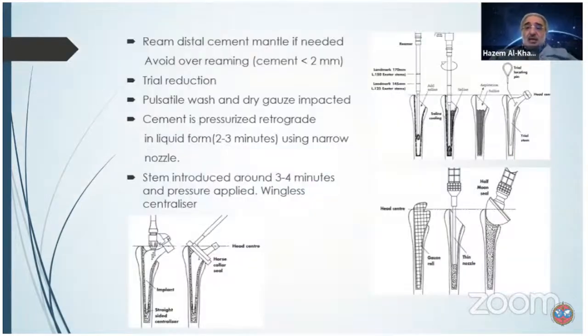And then, if needed for version or for size, you bur the acetabulum. You bur the femoral canal. You have to be very sure when you bur not to overbur, because you shouldn't go below 2 millimeters of cement. So the idea is to give it just the amount of burring which allows you to put the proper size and to have a rough surface, because this will aid in polymerization and the reaction of the cement. And then you have 1 minute left.